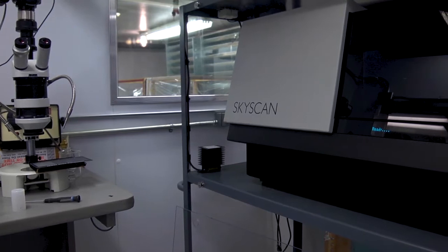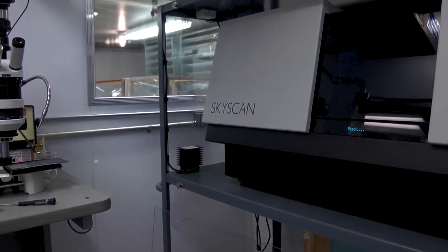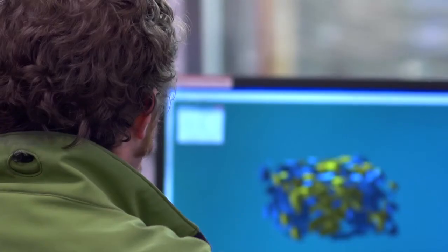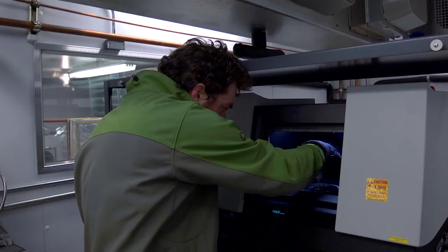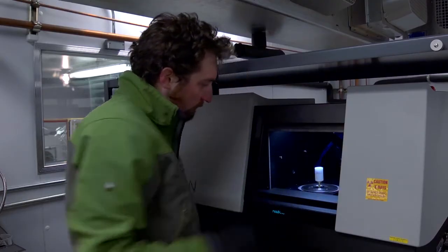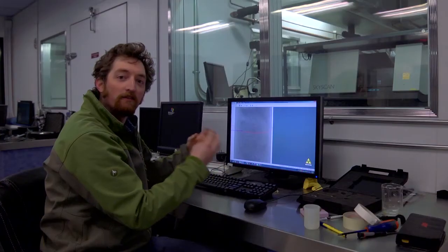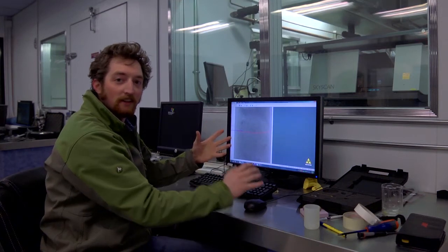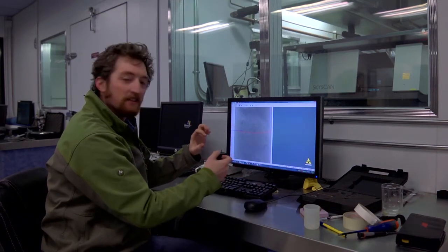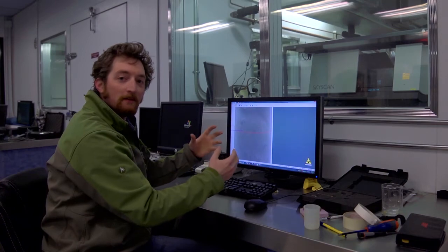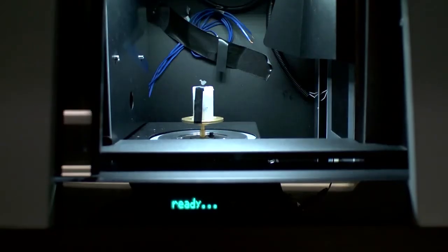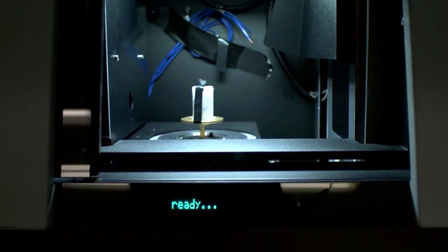There's equipment available to us to study the microstructure of snow that is not portable for the field. We can't lug a 500-pound CT scanner out into the field any day. The CT scanner offers us the opportunity to see the microstructure of the snow in full, glorious 3 dimensions. So we can actually look at every single grain and every single bond that's in the microstructure. It really allows me to look at what's going to go on during fracture.